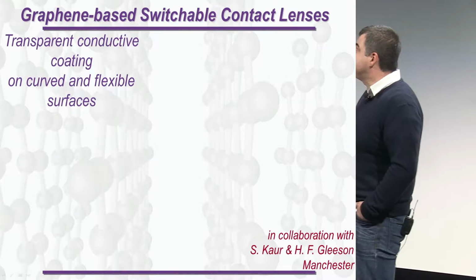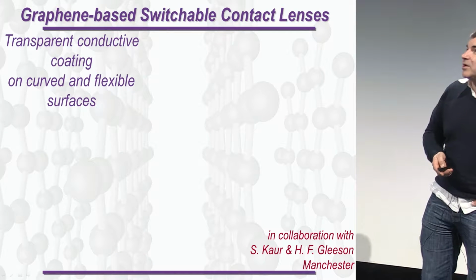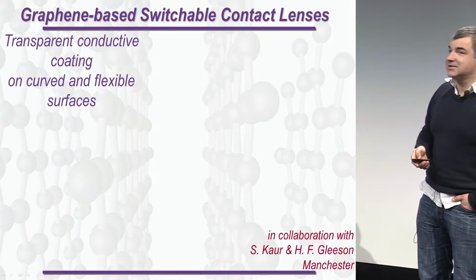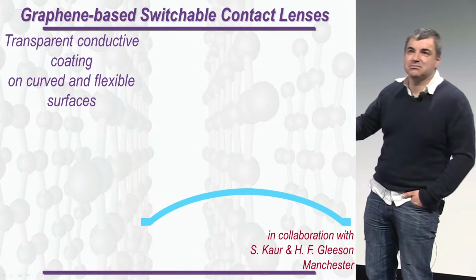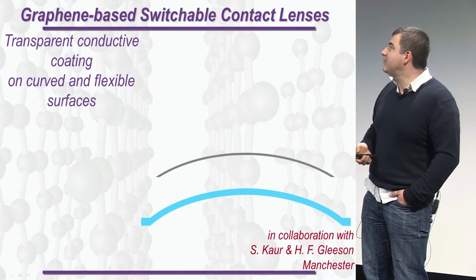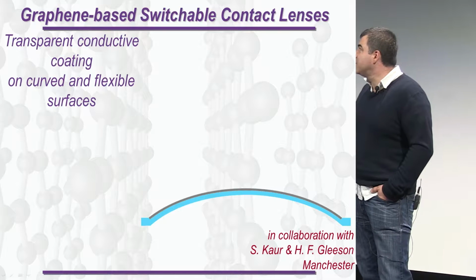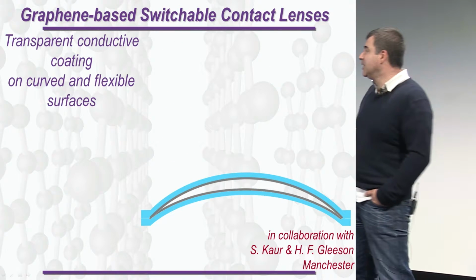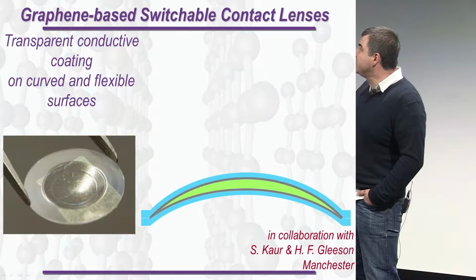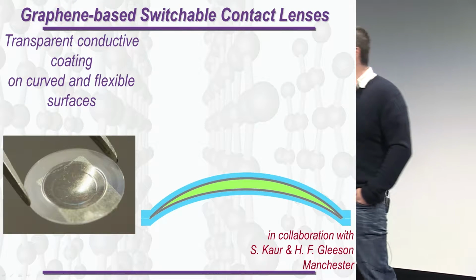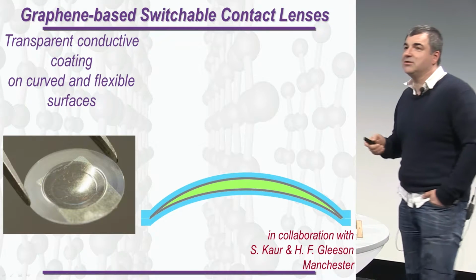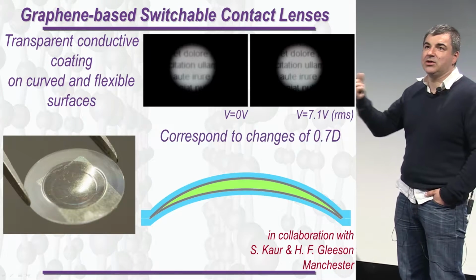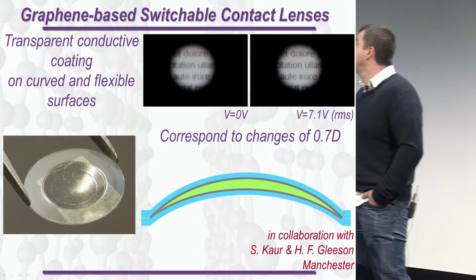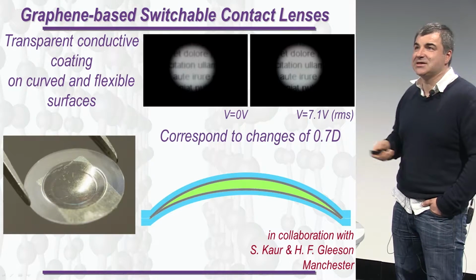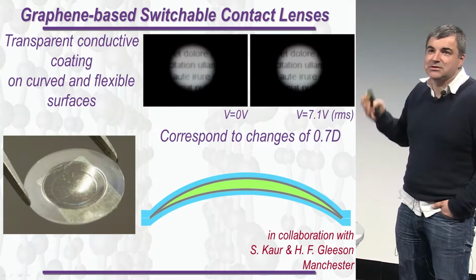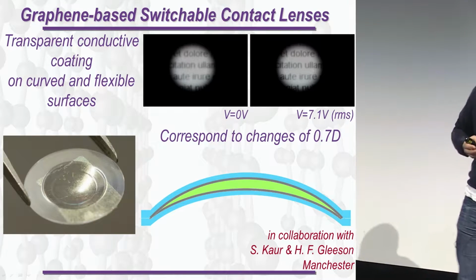And here is one of such applications. So we create adaptive contact lenses, and how you do it, you take a contact lens, basically plastic, PDMS, cover it with graphene, put another one on top and fill the gap with liquid crystal material. And basically, because you can apply voltage here, you switch the refractive index of this liquid crystal, and you can change the optical power, the focal depth of this lens. So you can change it by 0.7 dioptres, which is quite a reasonable number.